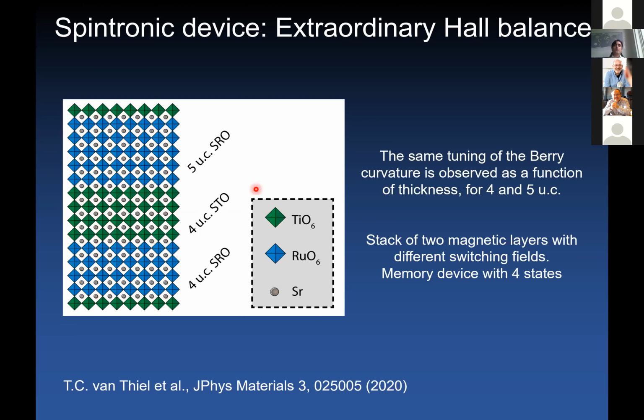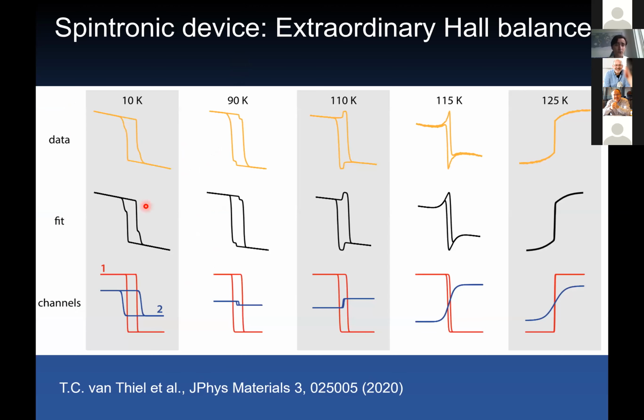Okay, so the same tuning of the Berry curvature that I discussed with the strontium iridate interfaces can also be observed by changing the thickness of the layer. So going from 4-unit cell to 5-unit cell, you can manipulate this sign change of the Berry curvature of strontium ruthenate. And if you create such a stacking, then you have a device in which you combine 2 transport channels that have different switching fields, and they have different signs of the anomalous Hall effect, and this can realize this interesting device in which you can switch your state of the anomalous Hall transport through 4 possible states, depending on the various arrangement of spins and signs of the anomalous Hall effect in your system.